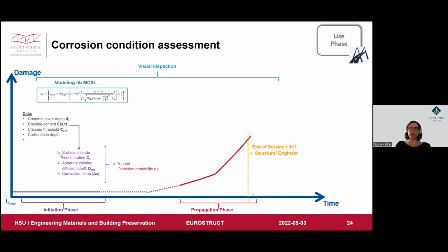As the next step, if you know now that your corrosion probability has probably increased, you could apply the half-cell potential measurement. This gives you information. It's also an inspection method which gives an indication of corrosion probability. And I will later on show a case study on how to deal with this data, because you can apply Bayesian theory in order to update your a priori corrosion probability with the half-cell potential measurement data. And this gives you very valuable information about your corrosion condition, not only time dependently, but also with the spatial variability of the corrosion situation on your structure.